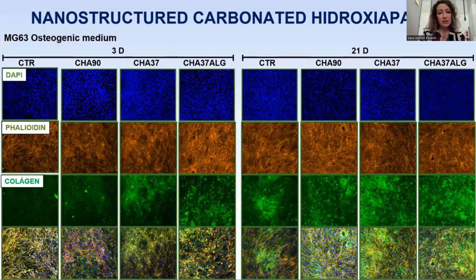After the material characterization, we exposed the bone cells to hydroxyapatite synthesized at different temperatures. So we show in these immunofluorescent images, with collagen staining, that the 37 degrees hydroxyapatite is able to anticipate the collagen formation. So it is supposed to be more osteogenic.